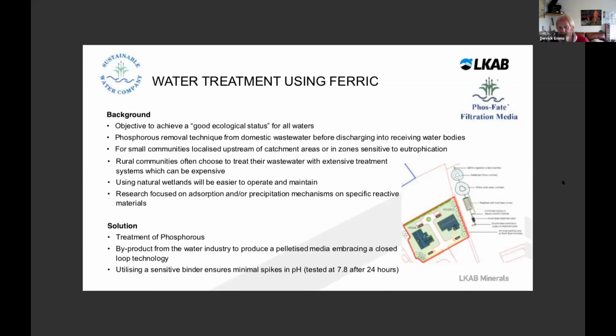We've utilised a sensitive binder which minimises the pH spikes, which was the big issue that we've had for a number of years trying to bring this product to market. It's always been pH issues in terms of discharge. Anything above 9 generally indicates that the water companies are not interested in working with you. So we used to have a product that was about 10, 12 on average, but we've managed to reduce that by bringing in this sensitive binder.